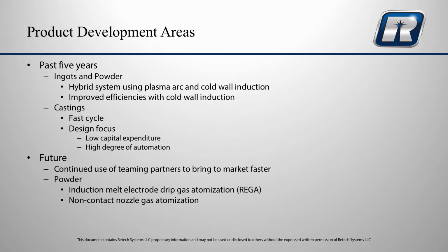That has to be fast cycle, and there has to be a design focus to keep the capital expenditure low and a very high degree of automation. We're going to focus not so much on castings, but on ingot and powder. In the future, we see a continued use of these teaming partners to bring it to market faster. With regard to powder, there's going to be some breakthrough. We're looking at induction melting, drip gas atomization, as well as some sort of non-contact nozzle gas atomization. I'll touch on those a little more later in this presentation. But those are the main product areas that we've been looking at.